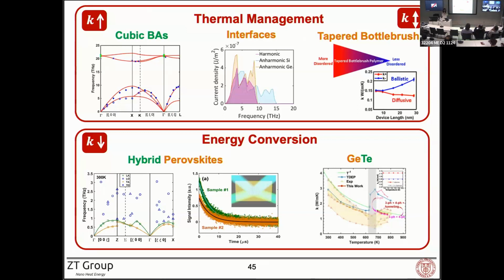And the reason we are not seeing the ballistic behavior converge to diffusive for the backward direction is because we haven't gone long enough. Due to the limitation of the computational resources, we only go up to tens of nanometers. But essentially what I imagine, if we do a long enough backbone, it will converge to the diffusive regime.